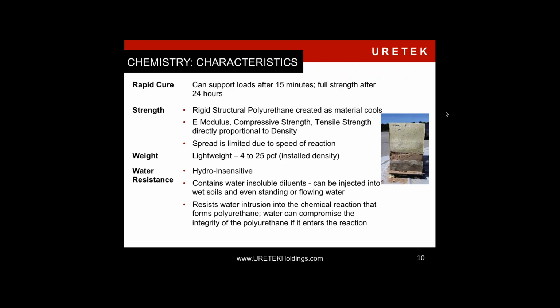Again, about 4 pounds, hydro-insensitive. The reason why it's hydro-insensitive is there are water-insoluble diluents mixed into the material. Not all high-density polyurethanes are hydro-insensitive or hydrophobic. You want to use a material that is hydro-insensitive, because if it's the opposite, being hydrophilic, they can continue to expand past injections. The material is fairly chemically resistant. The only real issue that the high-density polyurethane really has is ultraviolet radiation from the sun. Since we're placing it under structures and soils, the sun never really reaches it.